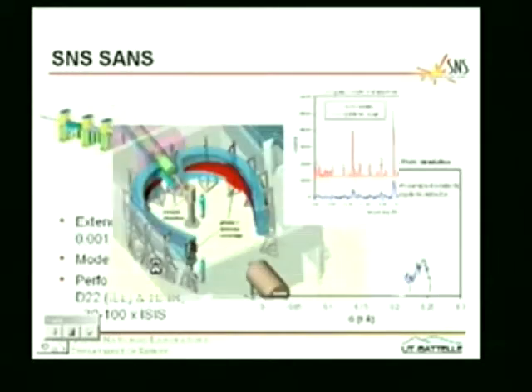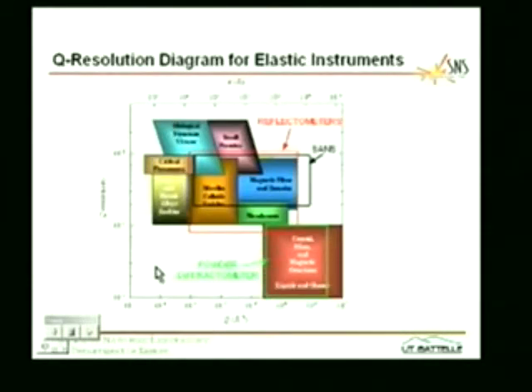If you do the same thing, I'm just skipping ahead here, for the elastic instruments, then this is plotted in terms of length scale, and it's a pretty wide range, about 0.1 angstroms up to about 10,000 angstroms. So it's the whole range of what we now call nanoscale phenomena, and Q resolutions that tend to be fractions of a percent. So quite good Q resolution, and this shows some of the scattering instruments, powder diffraction, reflectometry, and SANS. You have crystal structures, magnetic structures, liquids and glasses, membranes, magnetic thin films, and multilayers, micelles, colloids, vesicles.